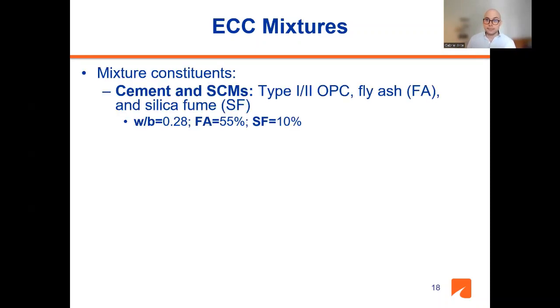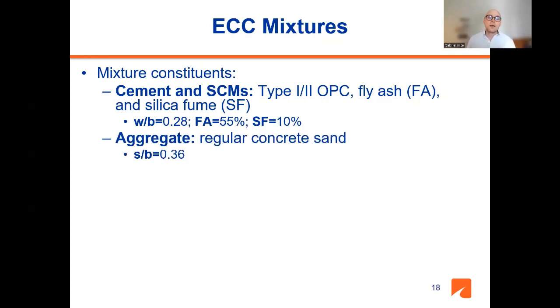Also, I wanted to give you a little bit of an idea of how these ECC mixtures look like. Again, this is ongoing research, but the mixtures that I'm about to present you are some of the mixtures that so far are looking promising for our application. The materials that we're using are type I-II ordinary Portland cement, fly ash, silica fume. The water to binder ratio is about 0.28. The fly ash content is 55% replacement of cement. Silica fume, we use it at 10% replacement of cement. And then the aggregate that we use is regular concrete sand instead of using this microsilica sand.